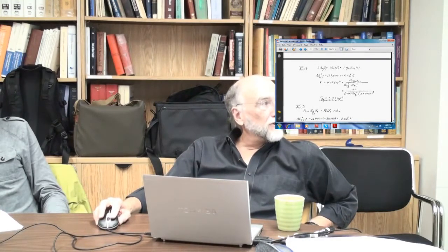But anyway, now you've replaced the silver by zinc, but now that's not a problem because zinc is more reactive than lead, so zinc can be reacted with chlorine. Now you can bubble chlorine through it, and that'll preferentially chlorinate the zinc because zinc is more reactive than lead. So you've replaced a less reactive element, silver, with a more reactive element, zinc, which you can then remove by the classical method. You don't use oxygen, you use chlorine for various reasons, but then you form zinc chloride and get rid of it. Okay.